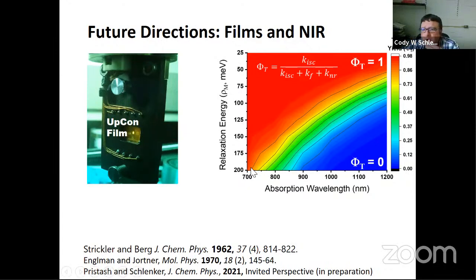And what was actually really surprising to us when we did all of this from the fundamental calculations of the kinetics is that for quite reasonable relaxation energies, which is basically 1/2 of the Stokes shift for these types of molecules, you can get to really quite respectable intersystem crossing yields for triplets, almost approaching unity. For parameters that have already been attained in the literature for dyes, you could pretty reasonably design a dye molecule that's going to undergo relatively efficient intersystem crossing. And so that's what we're doing now.